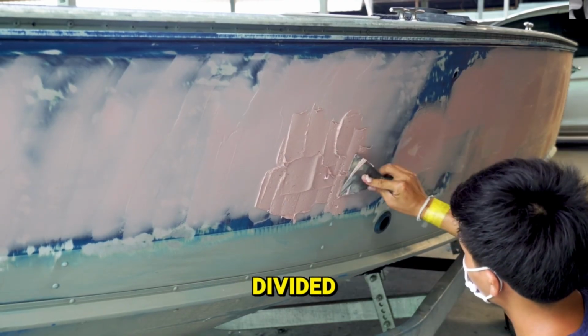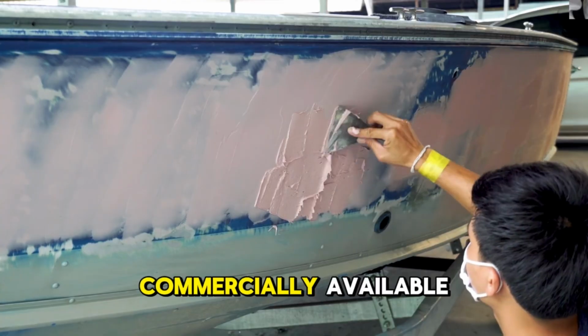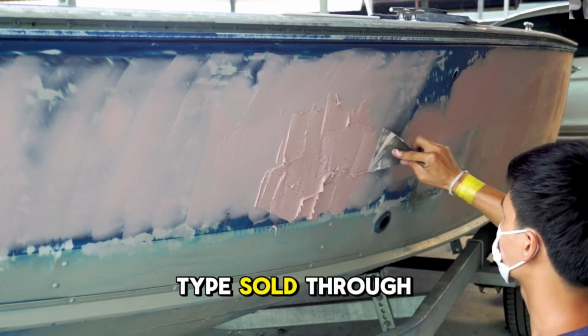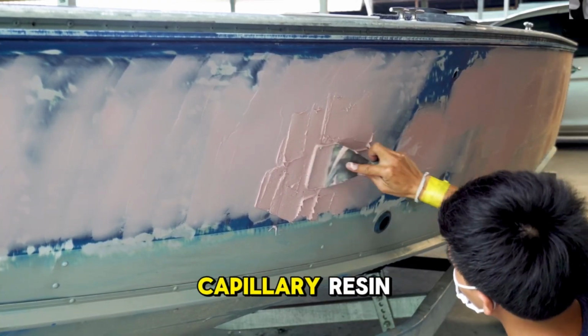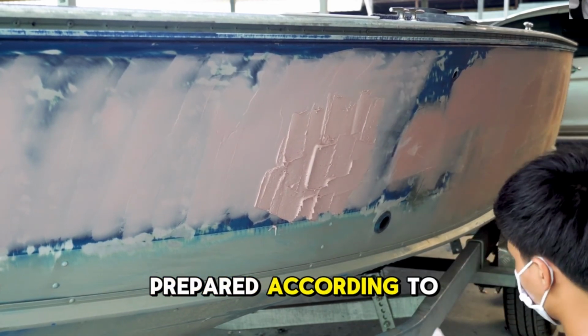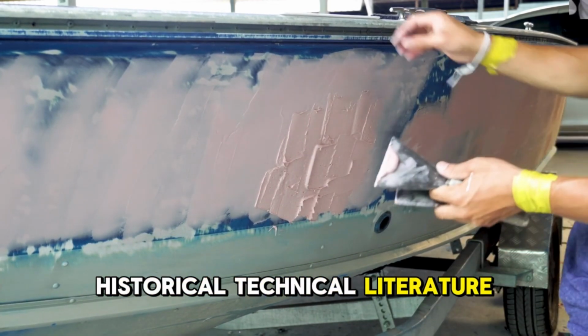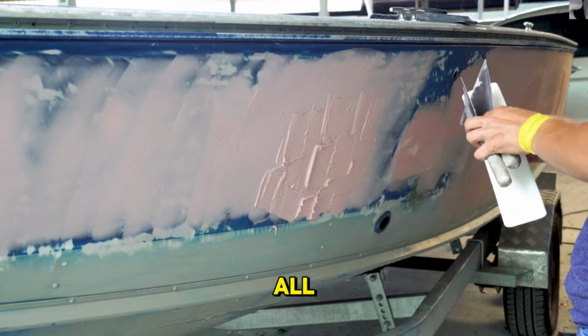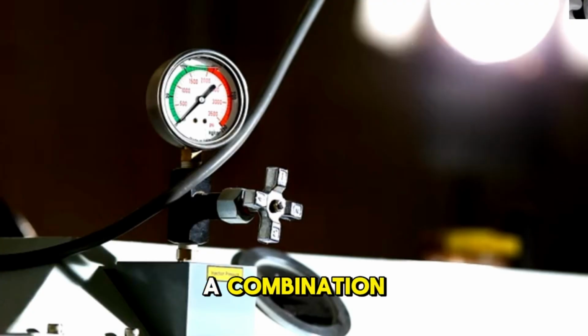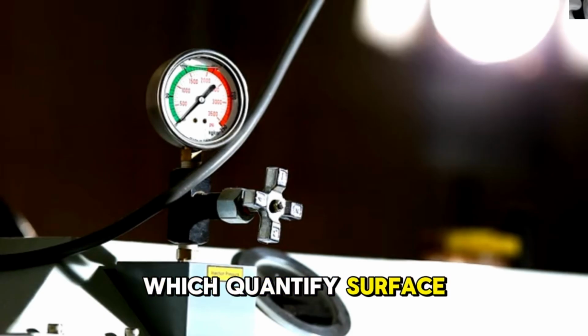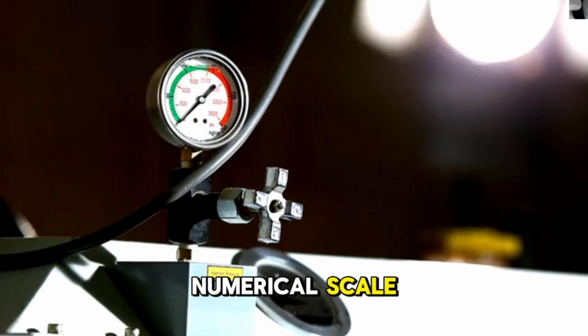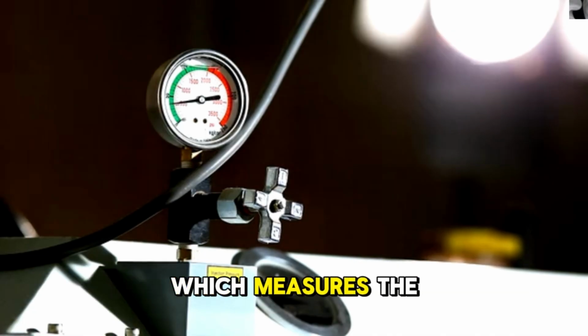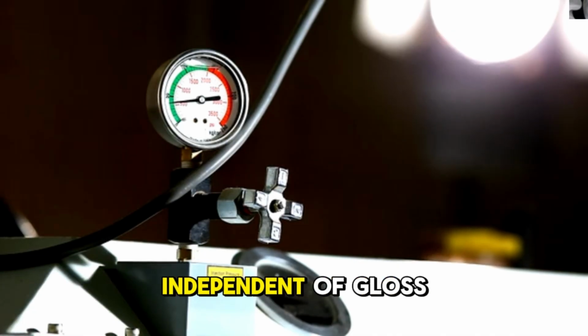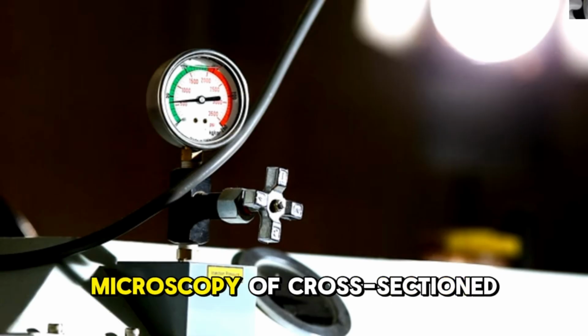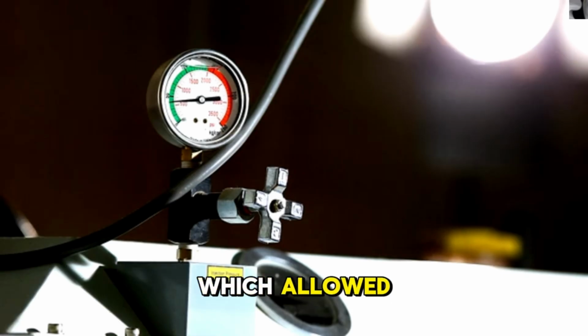At this point, the panels were divided into treatment groups, some receiving commercially available wax and polish products of the type sold through automotive retailers, some receiving a capillary resin infiltration treatment prepared according to principles derived from the historical technical literature, and a control group receiving no treatment at all. The measurements that followed were taken using a combination of gloss meter readings, which quantify surface reflectivity on a standardized numerical scale, spectrophotometric color analysis, which measures the accuracy and saturation of surface color independent of gloss, and scanning electron microscopy of cross-sectioned panel samples, which allowed direct visual examination of the paint film structure at the microscopic level.